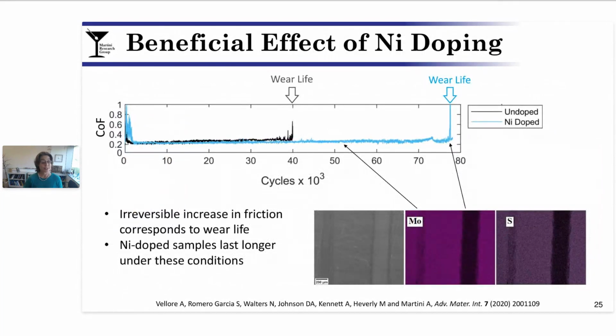Here we see a representative result. Again, this is friction coefficient versus sliding cycles. We see that prototypical or expected decrease at the beginning of the test. Long, steady state constant friction coefficient followed by a spike that corresponds to wear life. We performed an elemental analysis such that we confirmed that indeed that spike at the end, that high friction spike, corresponds to removal of the MoS2 from the wear track and therefore the life of the coating. But the key observation from this figure on the top of the slide is that the wear life of the nickel doped coating in the light blue is much longer in this condition than that of the pure MoS2.